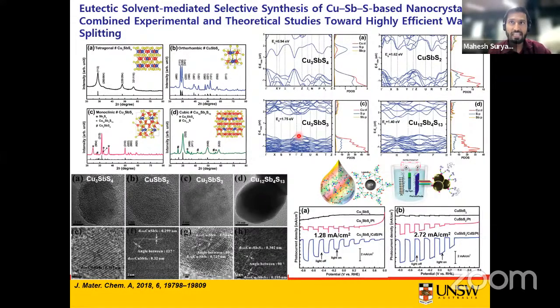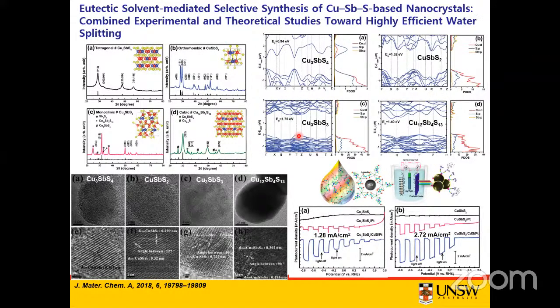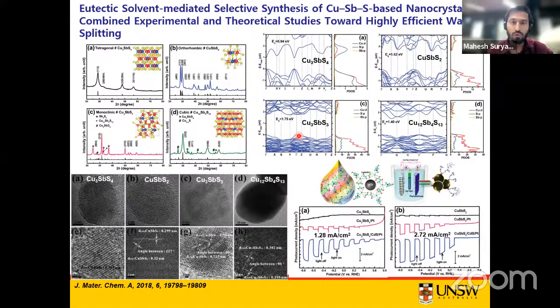So we used ethylene glycol based deep eutectic solvent, which has a low viscosity. The reason we moved our synthetic approach from vegetable oil to this low viscosity deep eutectic solvent is that in our previous experiments, we observed that there is a problem with the washing of the nanocrystals because of the high viscosity of the vegetable oils. You may also observe it in your kitchen. If you heat the oil, our cooking oil, let's say vegetable oil, to about 300 degrees centigrade, or let's say about 250 degrees centigrade, it becomes more and more viscous. And that's what we observed in our experiments as well.